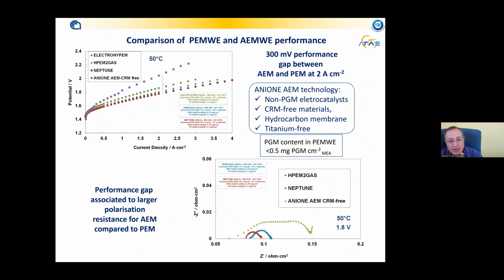You will probably be interested in understanding how AEM technology compares to PEM technology. PEM is very efficient, with low operating cell voltage at 2 ampere per square centimeter. In the case of AEM, there's an increase of cell voltage. The gap at a practical current density of 2 ampere per square centimeter is something like 300 millivolts. That is, at the moment, a significant gap, a significant drawback, essentially related to polarization resistance and electrocatalyst behavior.